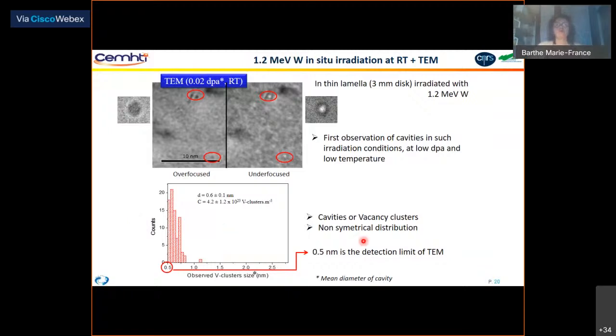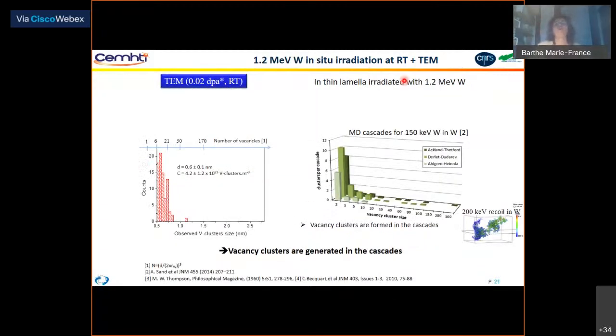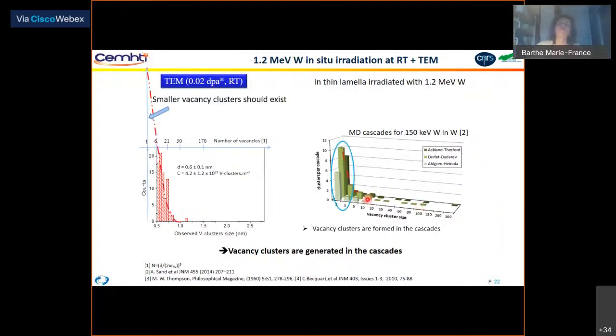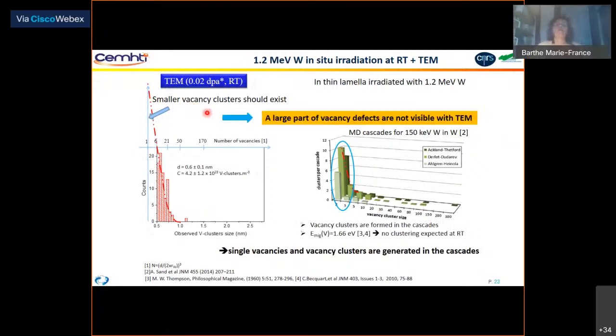this lower size part. So if we compare this distribution with molecular dynamics calculations of cascades in tungsten, you can see that this distribution starts from a single vacancy to different vacancy clusters. And if we draw this kind of distribution on our experimental one, of course, we should expect some smaller vacancy clusters. And of course, these smaller ones are not visible with TEM.